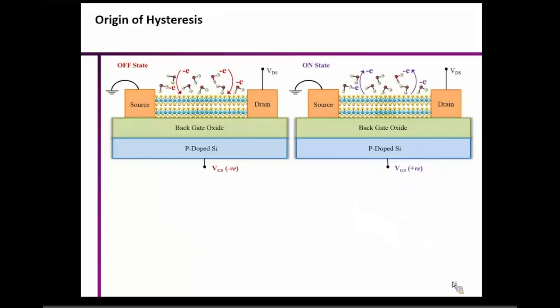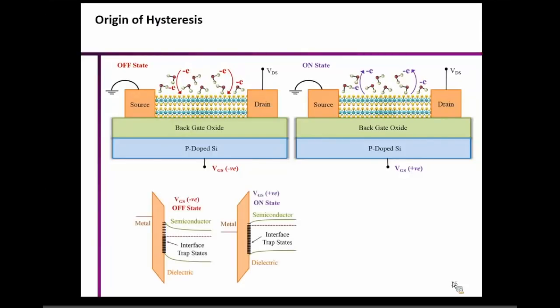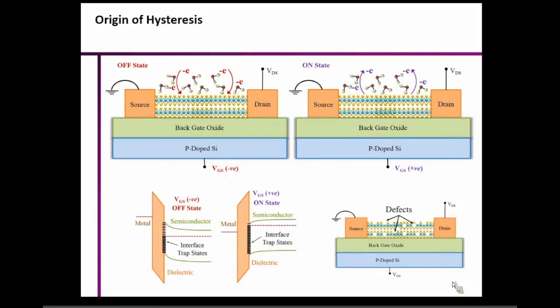But I will not go into much more detail, and I will just articulate the origin of hysteresis, which comes because our 2D material is not ideal. There is an interface with air, and we can have adsorbents on the 2D material. Our interface with the silicon dioxide in the back gate is not ideal, so there could be interface trap states, and the 2D material by itself also has defect sites. So all this could give rise to these non-ideal effects. We always look for optimizing or making these materials better, but maybe we can work with a crappy material which will give us this neuromorphic action. So that's the philosophy behind using these materials for neuromorphic applications.